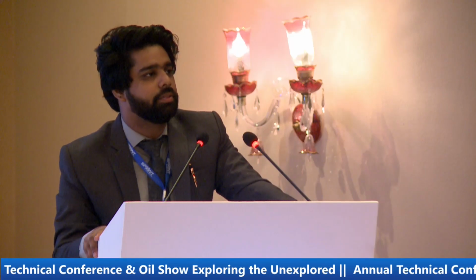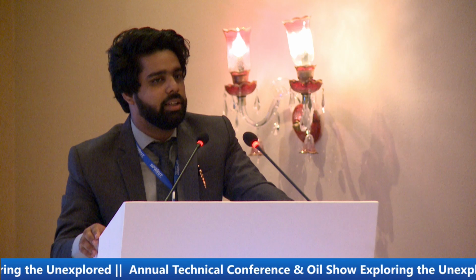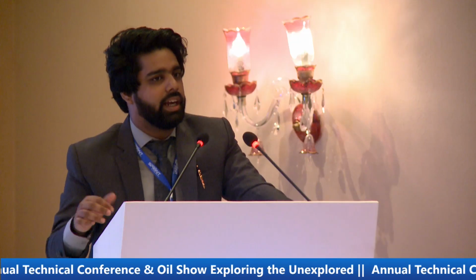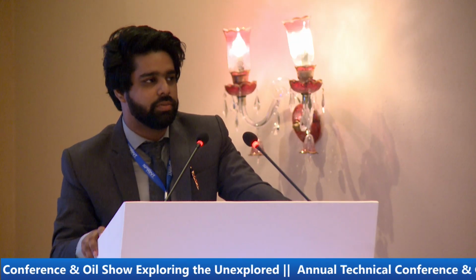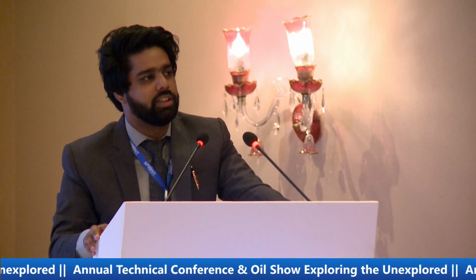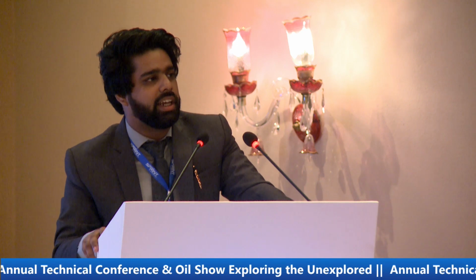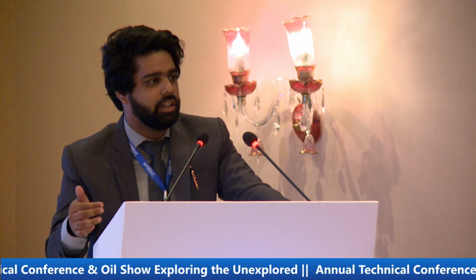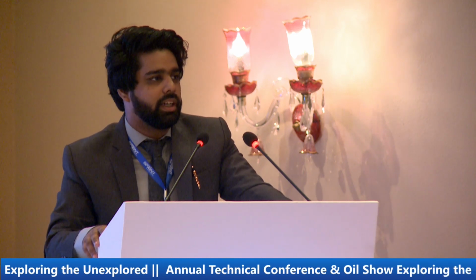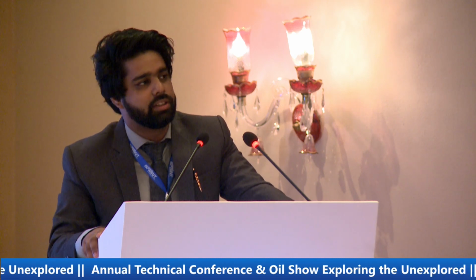Basically, to answer your question, we first simulated the hydraulic stresses that we will get while performing the job, and based upon those hydraulic stresses, we gathered the mechanical properties that the cement would achieve. So basically, considering the compressive strength, we usually incorporated expansion additives, which create some sort of expansion in cement, and during the process of cyclic stresses, the cement expands, and we had a provision to sustain those sort of stresses. So with the help of simulation and then with the help of designing, we have achieved those properties.